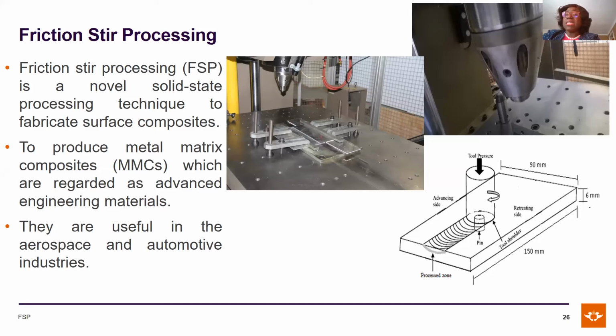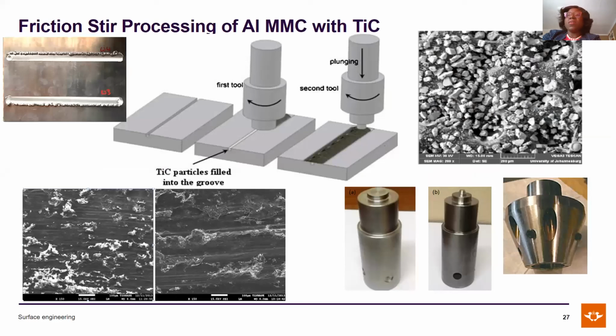The technology has also been used widely to produce metal matrix composites, and these materials have been regarded as advanced engineering materials, and they find applications in the aerospace and automotive industries. The way we produce our FSP is that we manufacture grooves in the substrate, the parent material to be used. We have grooves in them, and then we pour the powder materials that we want to use to reinforce the surface morphology into the groove. In this particular study, one of my students did this study, which I supervised.